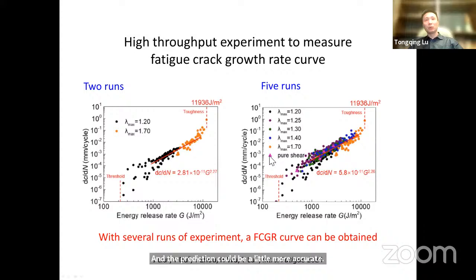Note that this figure also includes 4 triangles. The triangles mean the data points were obtained by the traditional pure shear test. So these 4 data points cost 4 rounds of experiment, and all the other data points are from the 5 rounds of high throughput experiment. We can see with this setup, with just a few rounds of experiment, the FCGR curve, the fatigue crack growth rate curve, can be obtained.